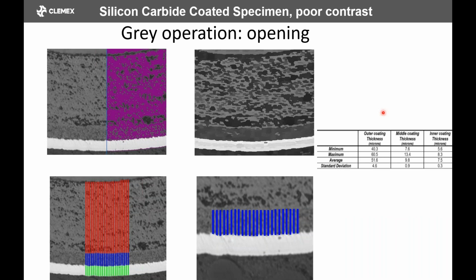Another example here: we have a coating that is very similar in gray level. It's some kind of gray, but there's a little difference. We can see that we have a texture here that is smoother than here, where we have the porosity and the texture. So we do a gray operation called opening, and then we can enhance those two layers differently because of their original texture. When we threshold, we see only the final result here, but the ceramic would be red, the silicon carbide would be blue, and the white layer would be green. So we can see that we can detect them properly, as we can see in this magnified image.